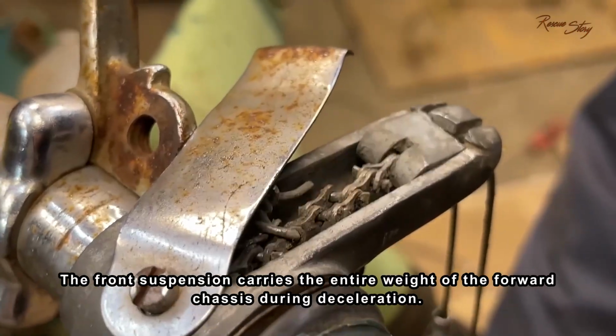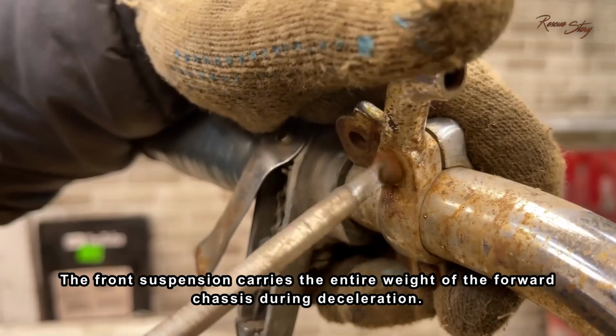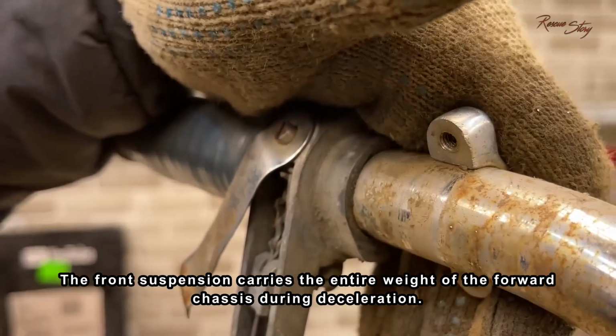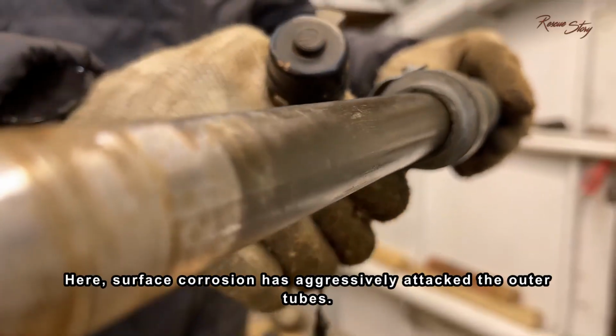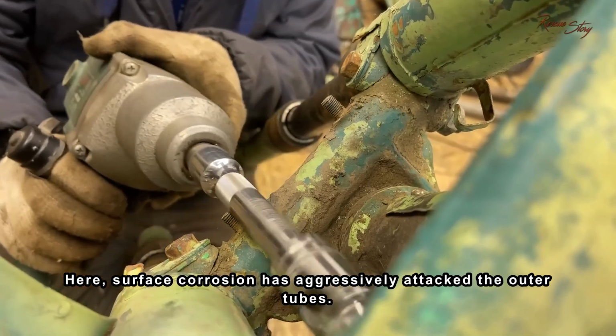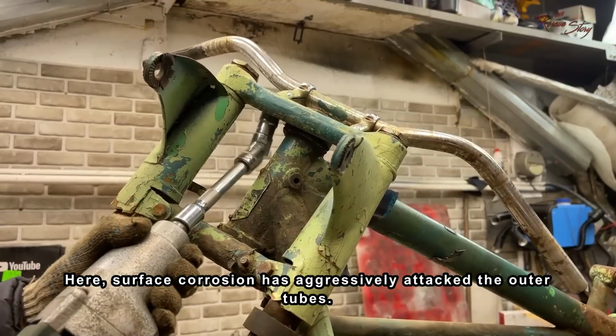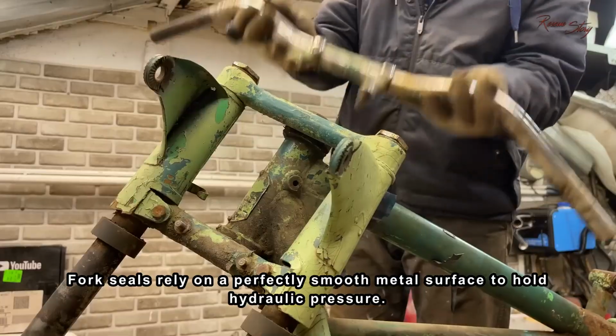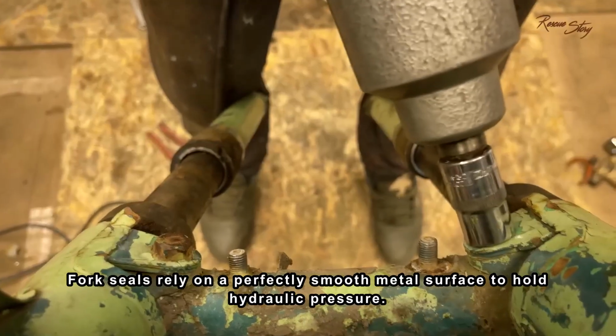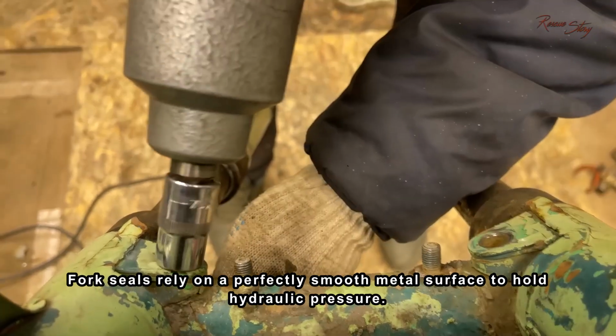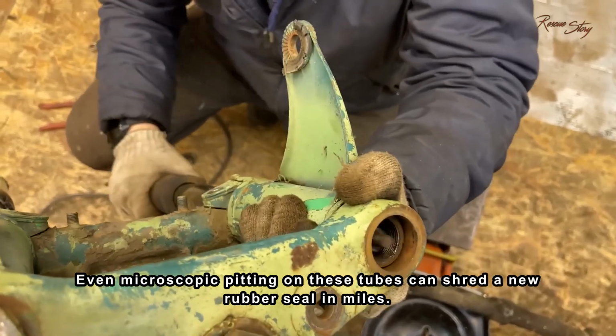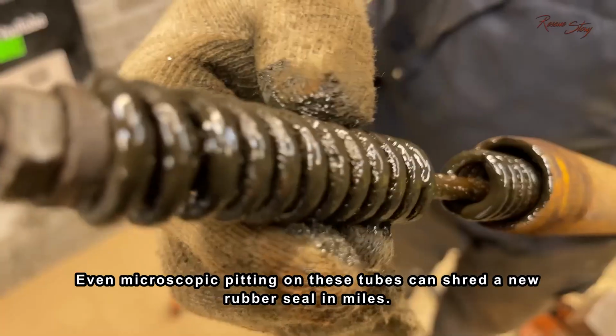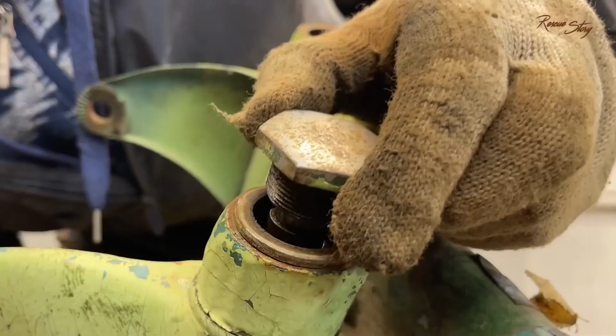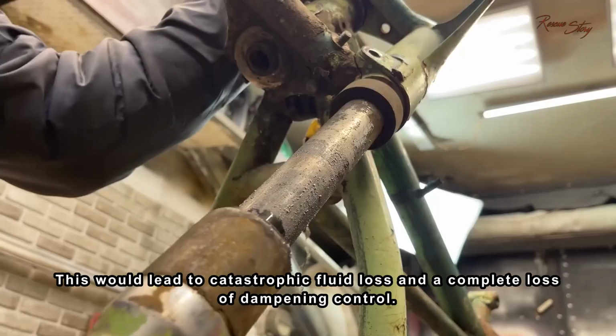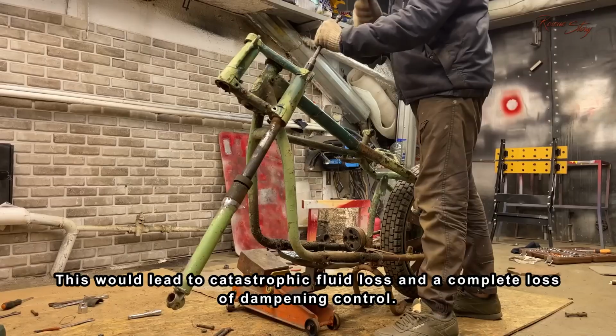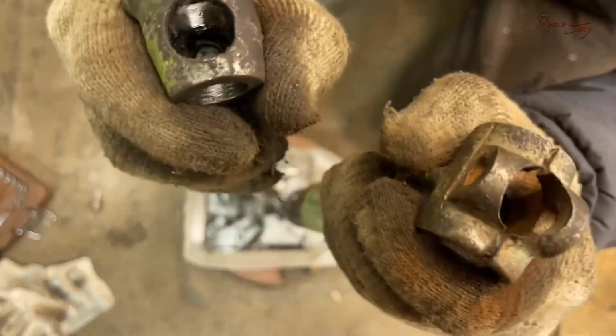The front suspensions carry the entire weight of the forward chassis during deceleration. Here, surface corrosion has aggressively attacked the outer tubes. Fork seals rely on a perfectly smooth metal surface to hold hydraulic pressure. Even microscopic pitting on these tubes can shred a new rubber seal in miles. This would lead to catastrophic fluid loss and a complete loss of dampening control.